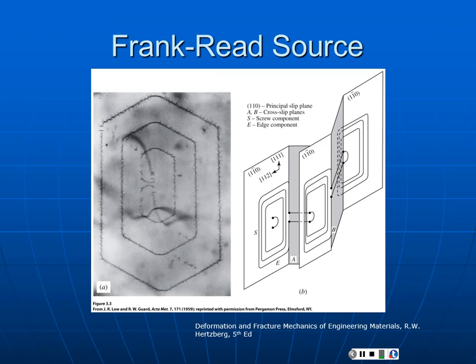But here's a transmission electron micrograph of a Frank-Read source at work. There's a boundary going on here that gives it the funny squared-off corners. But the point here is you see everything we're talking about, the loops forming, blowing up. And this then is an extra half plane. Each of these represents, you're looking down on an extra half plane of atoms that grow down into the material. And this is generating dislocations.